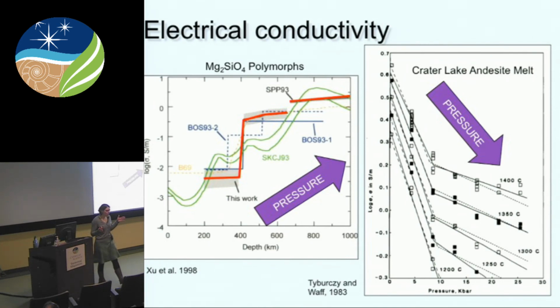And how we understand this is that as you compress the structure, you're basically shortening the hopping distance for the atoms to move through the crystal structure. So that's why we have an increase. In contrast, here's conductivity again as a function of pressure for a silicate melt. And what you can see is that as we increase pressure, we see the exact opposite behavior. You actually see a decrease in the conductivity. It's harder for the atoms to move through the system.